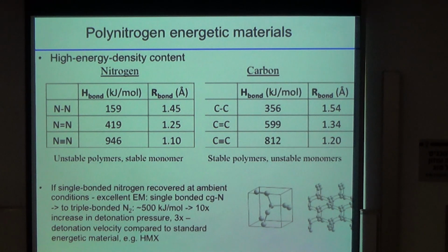If you have this metastable structure, a single bonded metastable nitrogen-nitrogen structure, and we provide some stimulus, it must decompose into N2 molecules. And this huge difference in terms of the chemical bonding must be released, right? So this is the difficulty with nitrogen-nitrogen, because it's difficult to get single bonded nitrogen. Okay, so we know that the polymers of nitrogen are unstable, stable monomers.